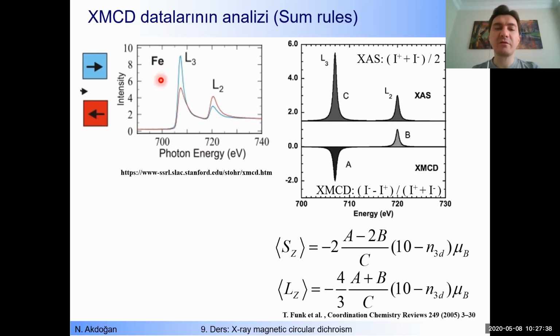And you use right circularly polarized light, blue one, and then scan that energy range, and you change the polarization to the left circularly polarized light, and then you scan the same energy range again, okay? So what we discussed during the last lecture in XRMS, you can plot those two signals as an asymmetry ratio, okay? Do you remember the asymmetry ratio we discussed in XRMS experiments?